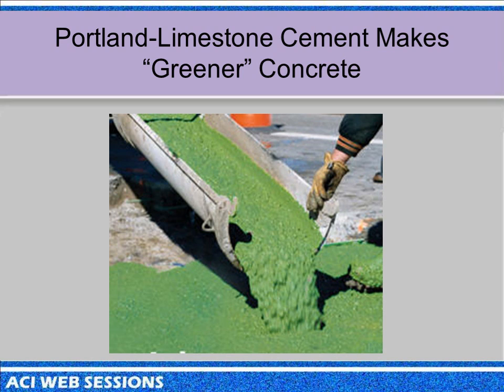Yeah, certainly. When we did our literature review before we adopted this in the Canadian Standard, one of the concerns was there was a lot of conflicting literature on the role of carbonate fines in sulfate resistance, especially at colder temperatures, because of the potential threat of thaumasite-type sulfate attack, which occurs at low temperatures in the range of 40 to 50 Fahrenheit seems to be optimum.